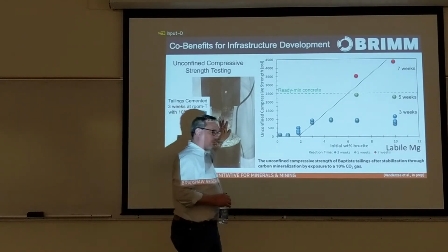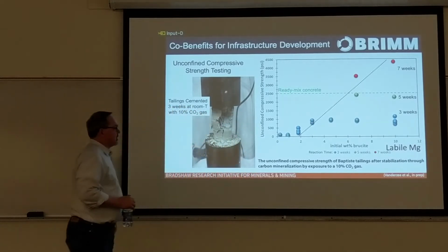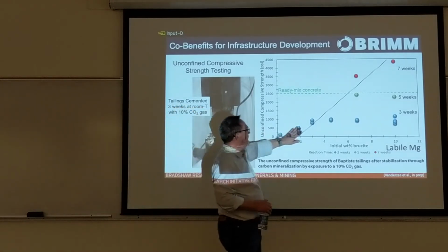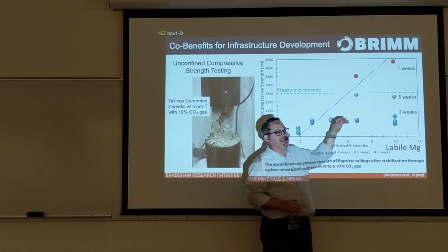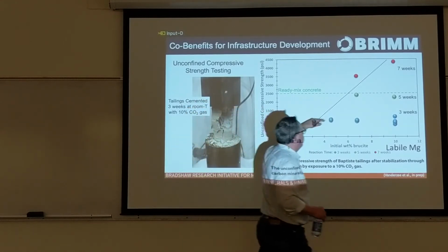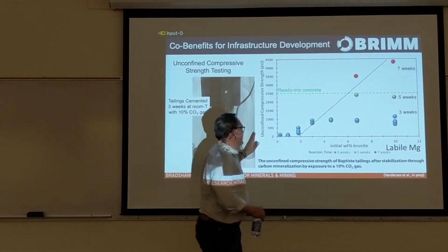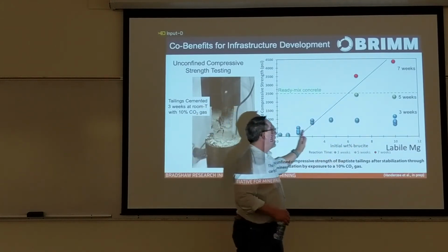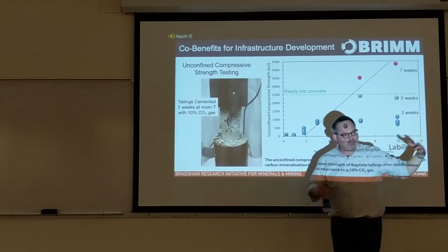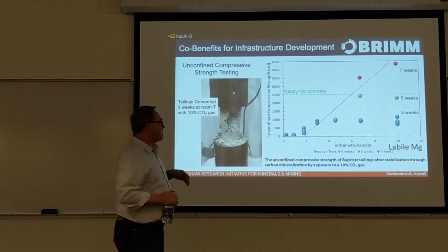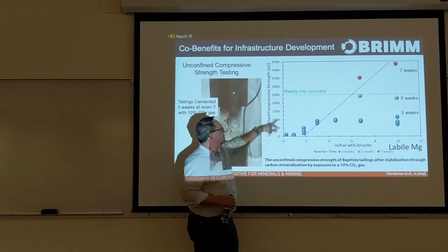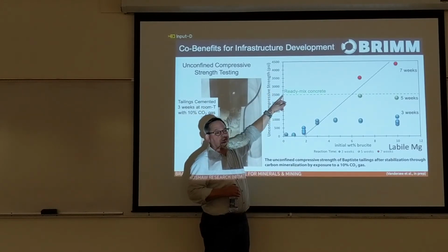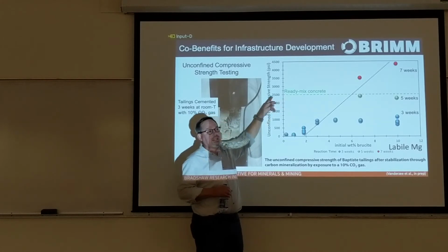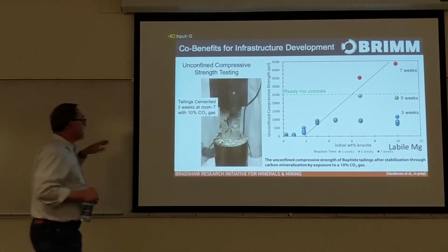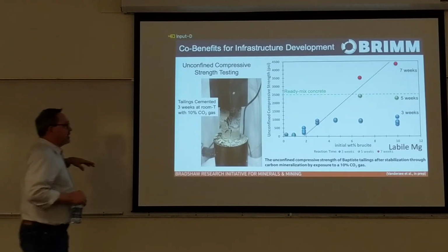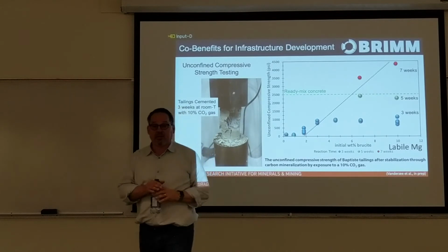So this is cemented nickel tailings from the Baptiste deposit that Sterling Vandersee is working on for his PhD. So we take tailings and we expose them to 10% CO2 at room temperature and pressure for 3, 5, 7 weeks. This axis here is effectively labile magnesium. The higher the labile magnesium, the longer it takes for the CO2 to penetrate deeper into the sample. We get more CO2, and we get an unconfined compressive strength in excess of what would come out of your Lafarge truck if you were pouring directly. So we get cemented tailings that have an unconfined compressive strength, in some cases, approaching high-strength construction cement.